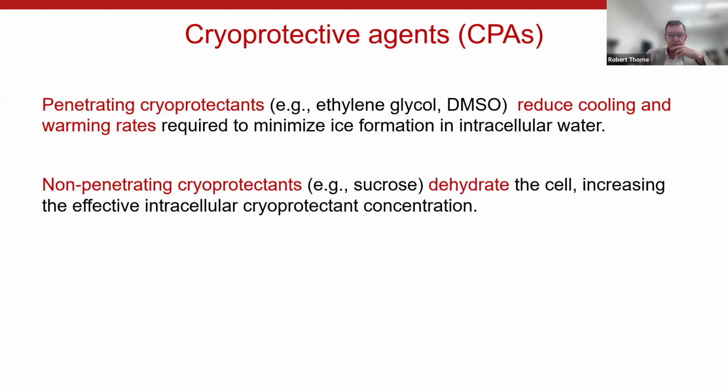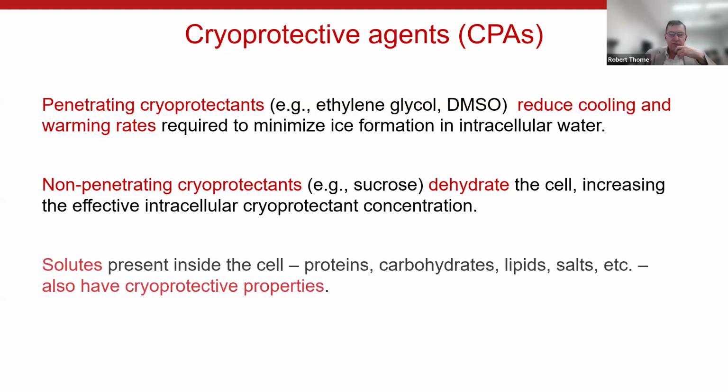Non-penetrating cryoprotectants, as you know, things like sucrose, dehydrate the cell and thereby increase the concentration of everything else inside the cell. And that includes whatever penetrating cryoprotectants you have, as well as whatever solutes are inside the cell, all the proteins, carbohydrates, everything but water inside the cell. And it turns out all solutes have cryoprotective properties.